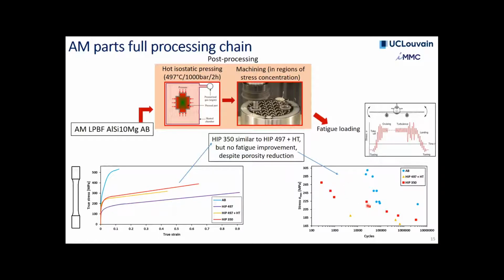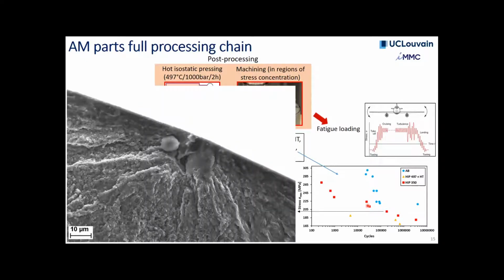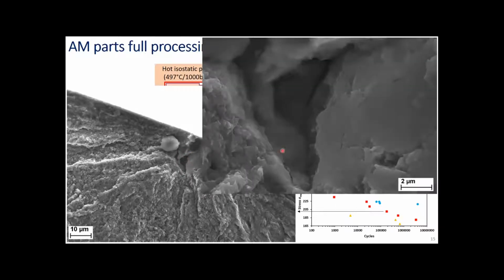Now, we thought that, having reduced the porosity level, we would expect to have a better fatigue life. And so we looked into the fracture surface of one of these samples here. And as you can see here, I'm going to zoom on this one. It actually shows a porosity, but you can see this porosity seemed to have opened. So our feeling here is that this hot isostatic pressing actually closes the porosities, so you don't see them anymore when you're doing tomography. And I didn't show you any images, but we did confirm that it reduces the porosity level. But these are just closed; they're not sealed in any way, or that is at least our feeling today. And so basically it reopens and it's making a very fine crack, as you can see here.